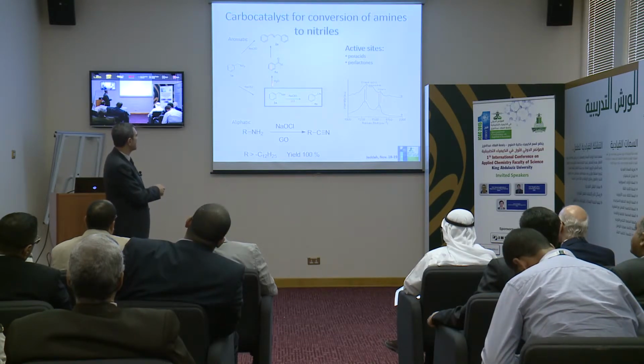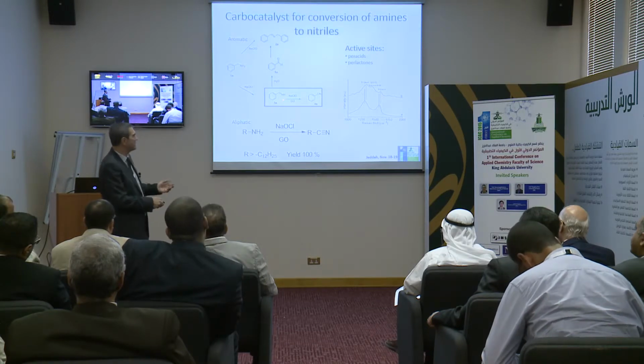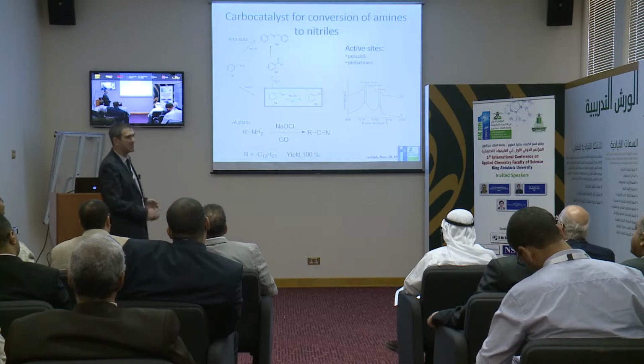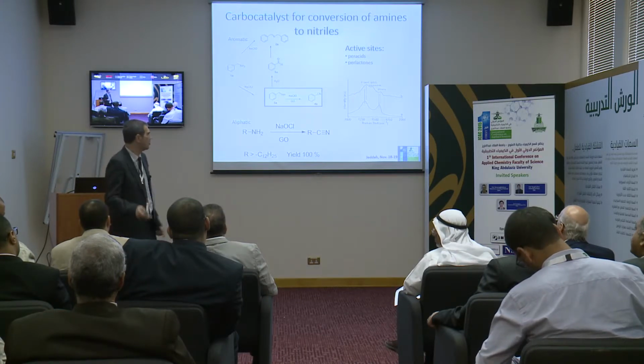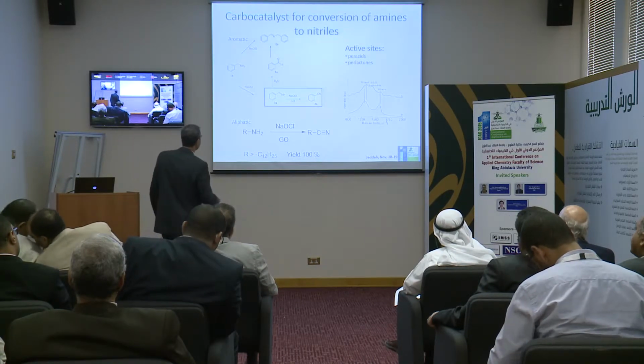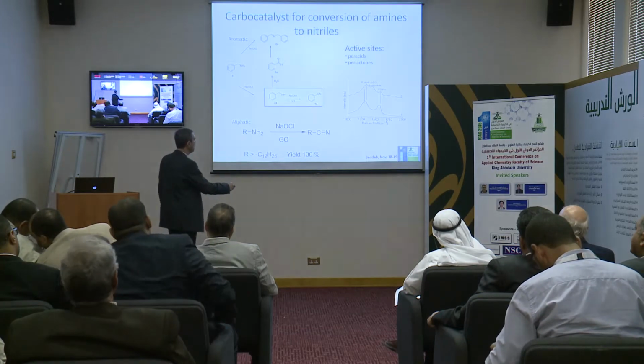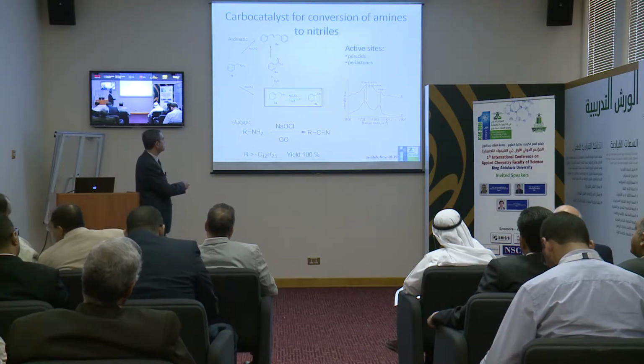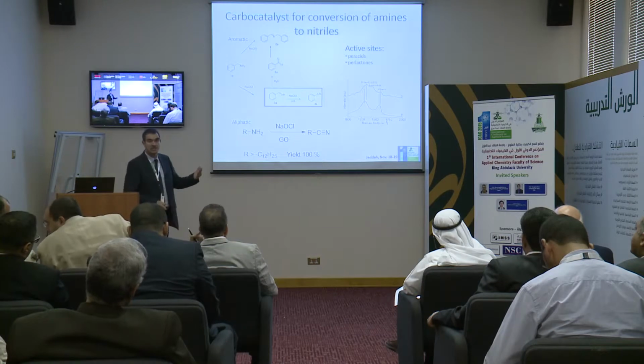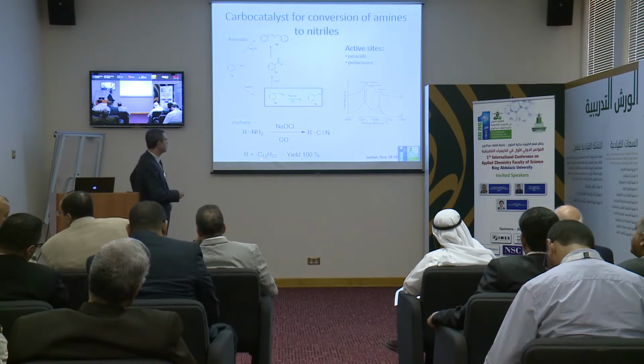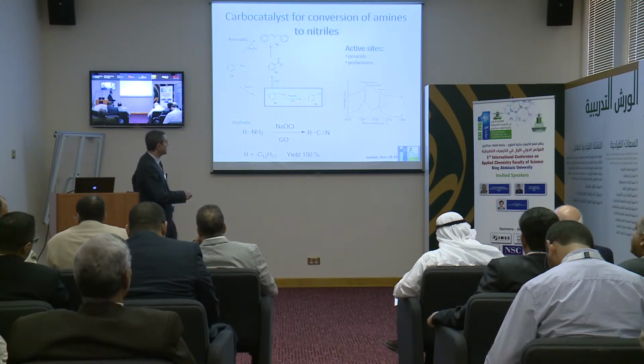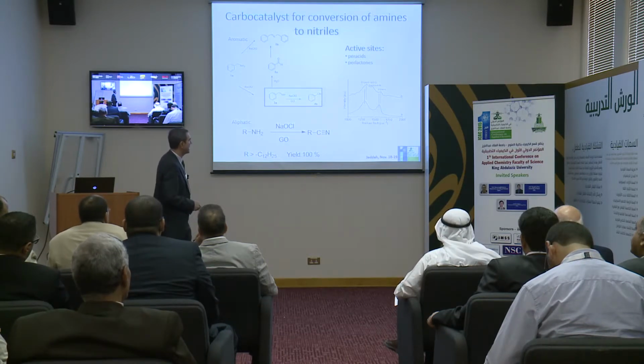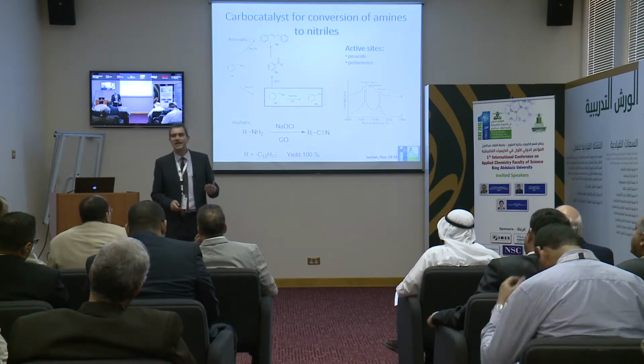So we have determined the reaction mechanism, and we have established that here is the rate determining step that requires the action of a catalyst, and in this case graphene oxide is a good catalyst for the process. In the case of aliphatic amines, the reaction works very well, particularly for long chain amines that are the most interesting ones from the industrial point of view, and in this case the yield can be 100% for the formation of the nitriles. Again, what are the active sites?